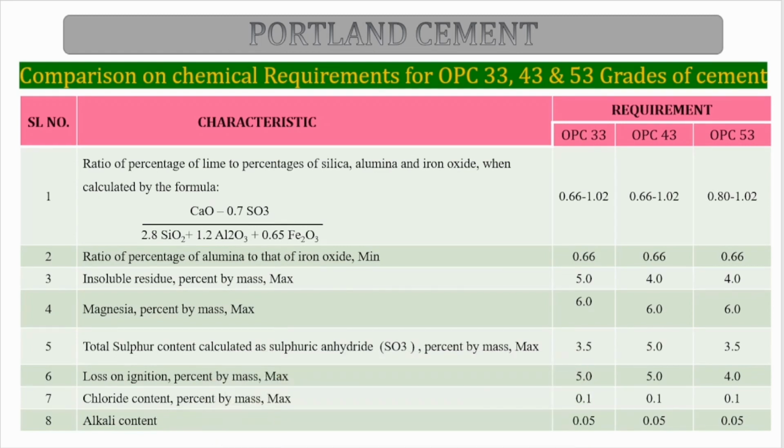We have already discussed earlier the main constituents of cement, that is lime, silica, alumina and iron oxide. Now, there is an approximate limit fixed for the chemical composition of cement. As you can see all the values over here, this is from the IS code books. Any change in this limit may lead to a change in the behavior of the cement. For example, suppose we increase the lime content, it makes it difficult to combine completely with other compounds. This also may lead to an increase in free lime, which finally results in an unsound cement, and that is practically not acceptable.